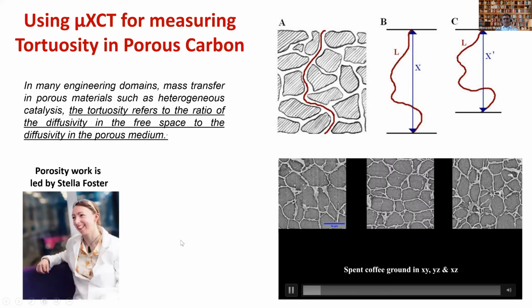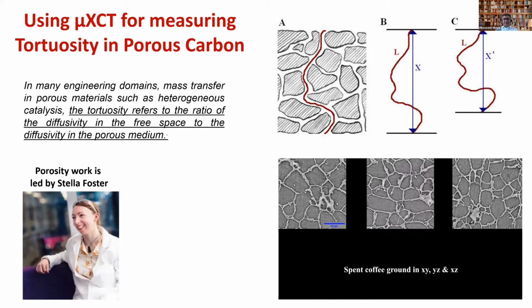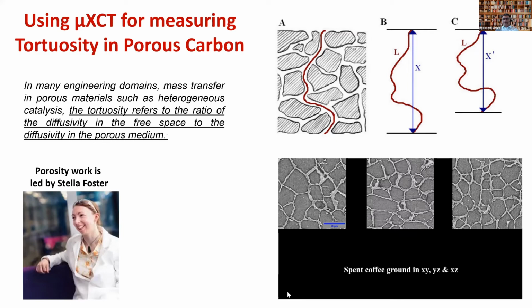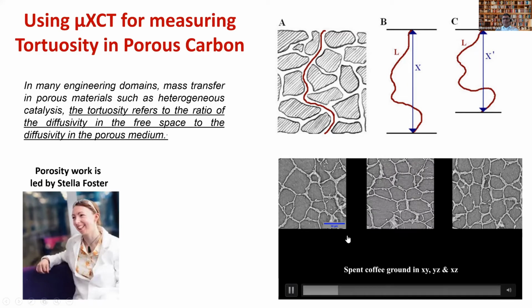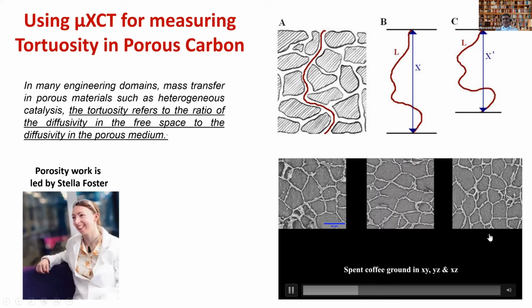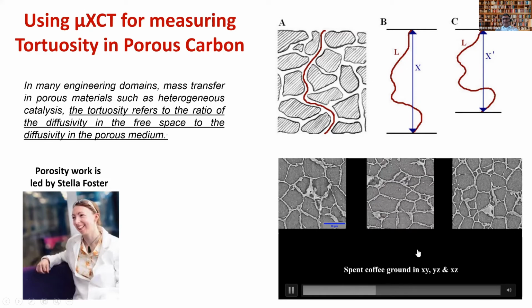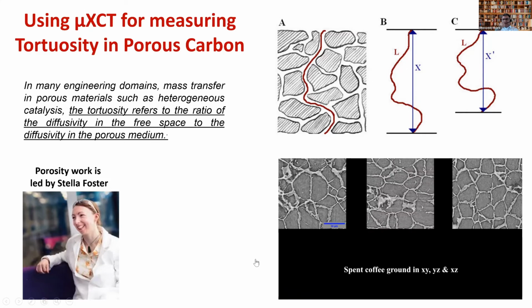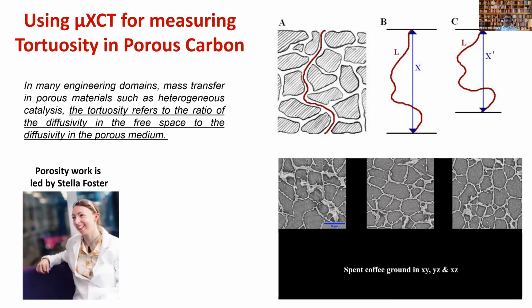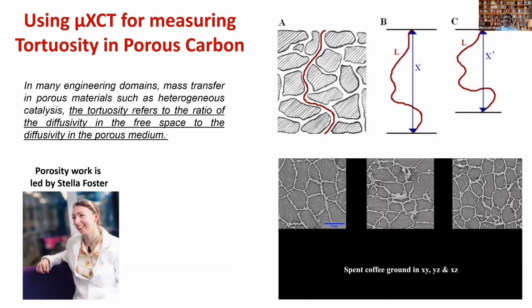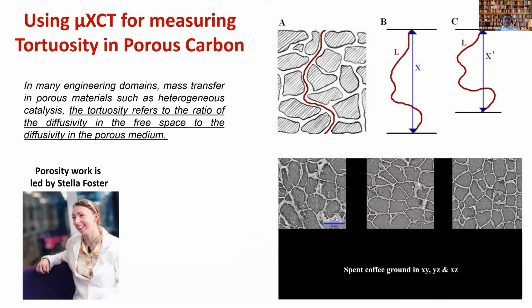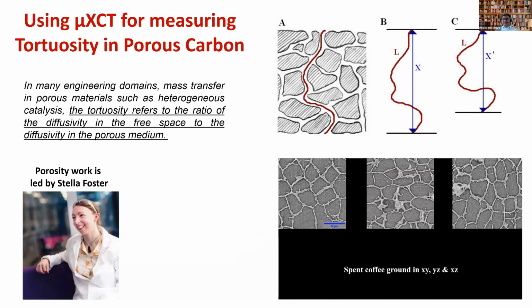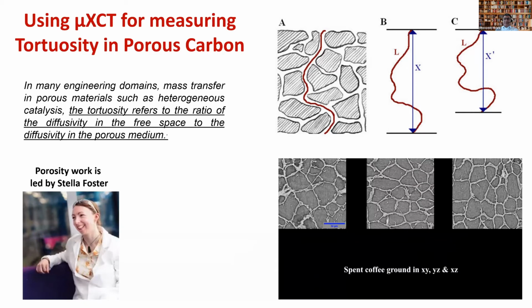So this is, we see in X, Y, and Z plane. Okay. So this is XY plane, YZ plane, and ZX plane. And this clearly shows that they're not completely isotropic. So there's anisotropy in these materials. And that can either be a challenge for certain applications, or that can also be a wonderful thing for some other applications. So basically what this means is that you are going to have a preferred orientation in which the flow will be faster compared to others.